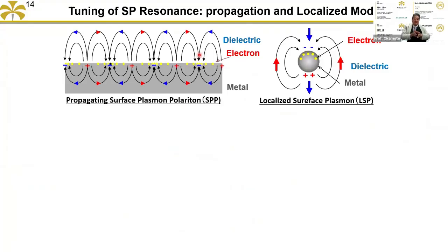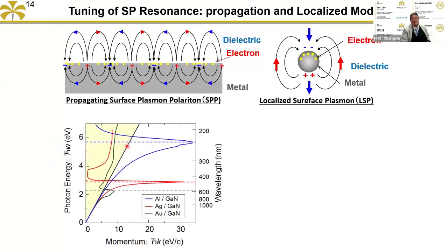And the next important thing is how to tune and how to control the resonance condition and the resonance wavelengths. That's very important. And as I said, there are two modes for the surface plasmon. One is the propagation mode and the other is the localized mode. The propagation mode is some kind of wave, that's why it has a dispersion diagram, momentum versus photon energy. And light can use only the region inside the light line, but the surface plasmon mode exists outside of the light line. That's why normally the coupling of the light and the surface plasmon is difficult. You have to make a nanostructure, and momentum matching is necessary.